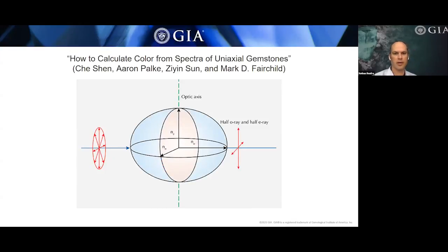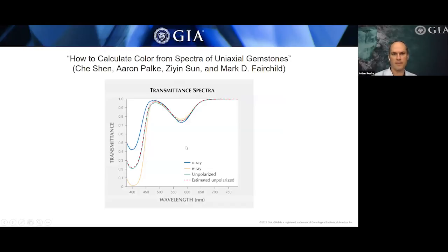This is one of their diagrams to illustrate how when light travels through a uniaxial crystal that's unpolarized, it becomes polarized, and then when it's perpendicular to the optic axis, you have half of the O ray and half of the E ray produced. So this is how they were able to measure the polarized spectra when the light is entering the sample perpendicular to the optic axis. And this shows how the corrected estimated unpolarized spectra matched the measured spectra better once they used the transmitted spectra method. So they fixed the error there.